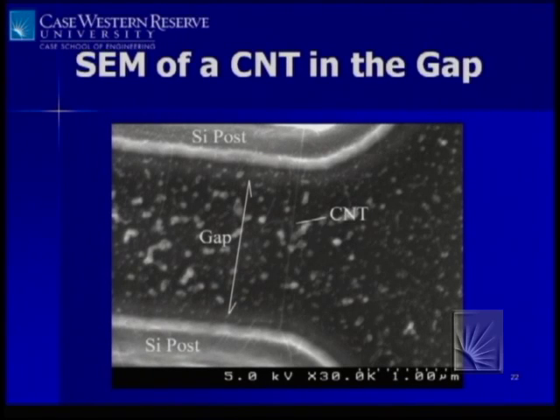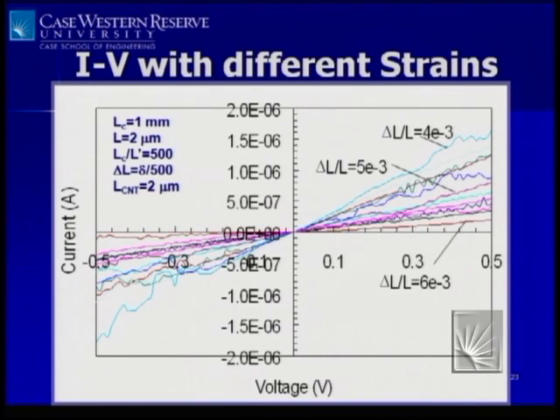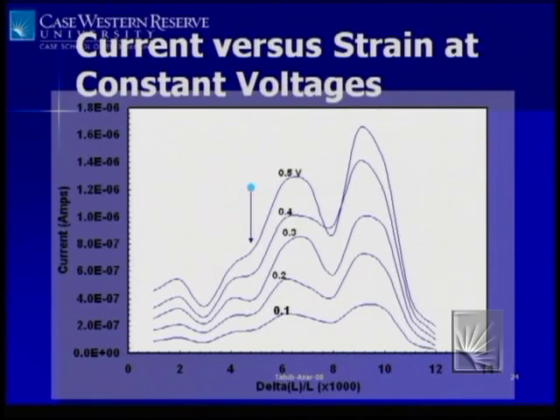So these posts come with this device for free, right? We look at the IV between these two posts, and you can see that the IV changes depending on the strain that you put on the system. Depending on how much you bend the cantilever beam, the IV has different slopes, which means different resistances. So I can look at current versus the strain as shown there, and you can see these modulations, ups and downs.